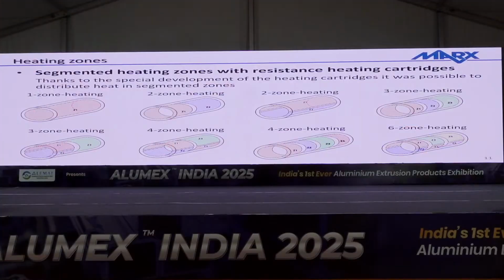These are some possible heating zones that can be reached with our heating cartridges. You have one-zone heating, you can also get 2-zone heating, one ring at the die side and one ring on the stem side. You can also have upper and lower shell, and also 6 zones with rings and upper and lower shells.